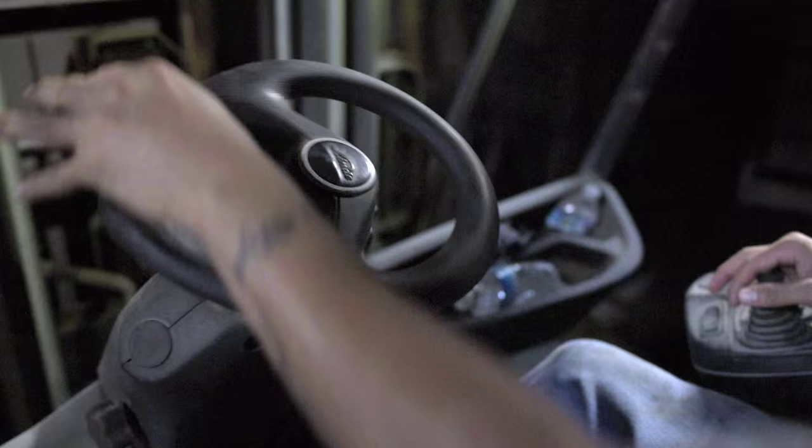We add a little water and make a zero slump concrete. It goes up into a bin hopper and down into the mold box. We vibrate all the air out, then convey those via forklift into kilns that are fired at 180 degrees steam, and we do that for about three hours.